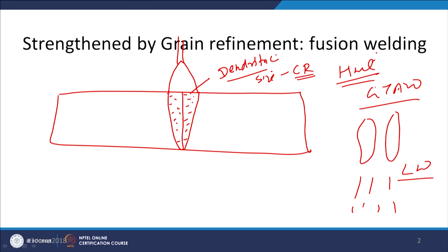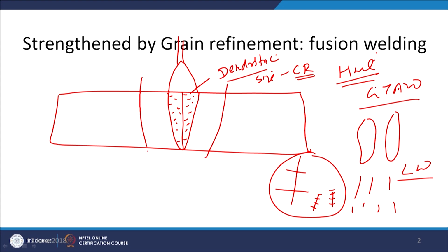Since it is an as cast structure, the dendrites are very coarse for gas tungsten arc welding, while in case of laser welding these will be very fine. Now, apart from the formation of the dendritic structure or the cellular structure in the weld metal, part of the heat will also be transferred to the base metal, and it will develop the heat affected zone on both the sides. Since this kind of metal system has been strengthened by grain refinement, the grain size is fine,